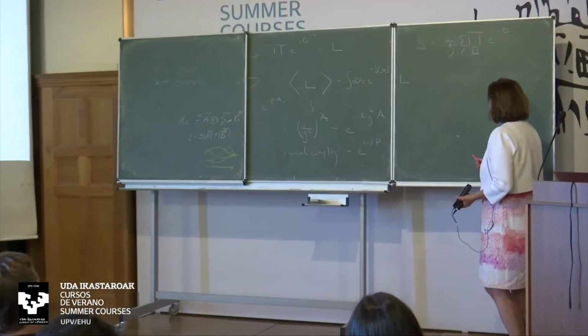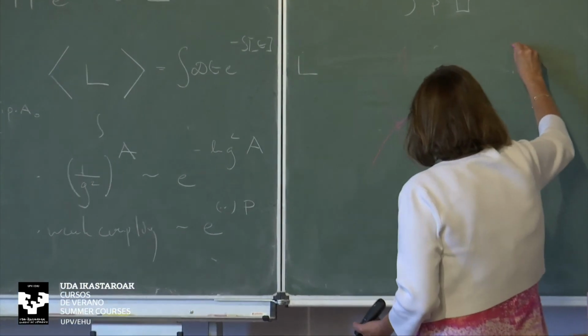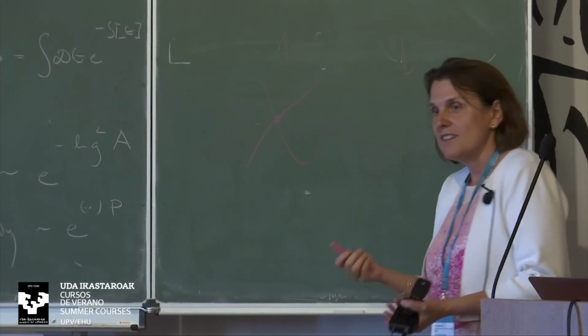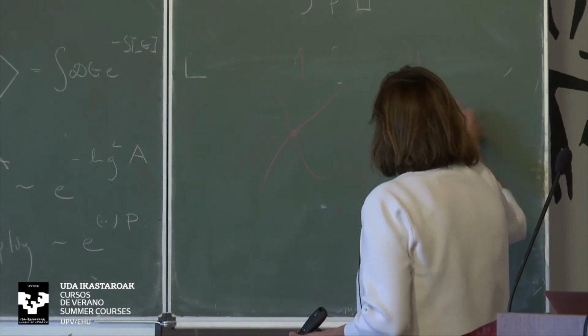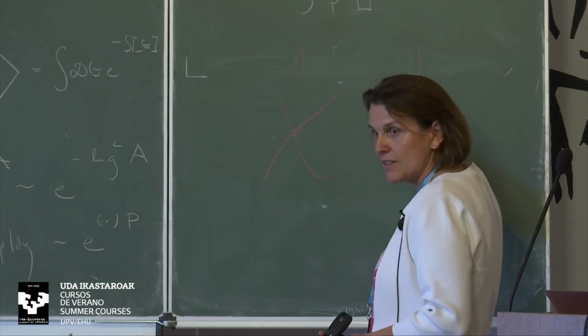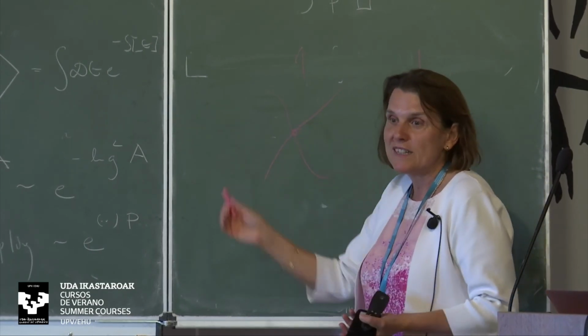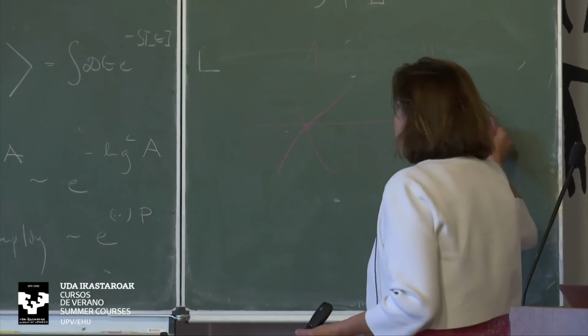But the nice thing with the Heuslers, if you have a half metal, if you assume spin, which you cannot do if you apply spin-orbit coupling, and if you do a Dirac calculation, then the spin is a bad quantum number. But you have a half metallic ferromagnet, which means you have a gap here, no states, and only states here. So you already have less spaghetti around the Fermi energy. Therefore, they maybe are better.